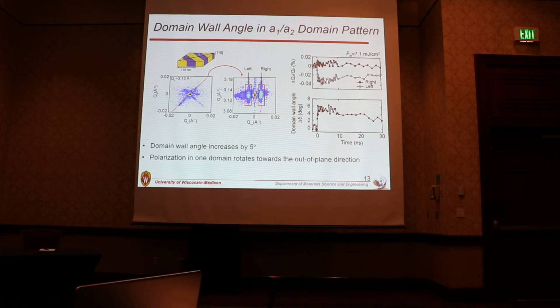And to understand this switching transformation mechanism, whether it proceeds with polarization switching or just transitions, we have measured the domain wall angle change by optical excitation in a1/a2 domain patterns.